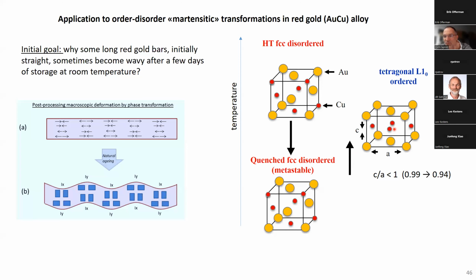have an organization of the copper and gold atoms with a lattice distortion. We have a contraction along this axis and a slight extension along this axis. It is a tetragonal phase with a c/a value lower than 1. We start with a value very close to 1, and if we leave it time after time, we organize the atoms and we finish with this c/a value.